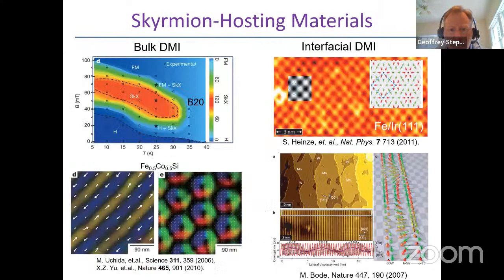So let me jump here. So the chiral interactions, the Dzyaloshinskii-Moriya interaction, is most commonly seen in bulk materials. There are a few bulk magnetic crystals in nature that lack an inversion center. And so these materials like iron, cobalt, silicon can, under appropriate conditions, so that is under appropriate ranges of magnetic field or temperature, exhibit a skyrmion lattice phase. And so there's a lot of interesting physics and potential applications in such material.